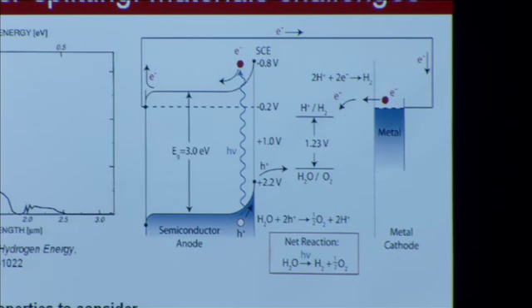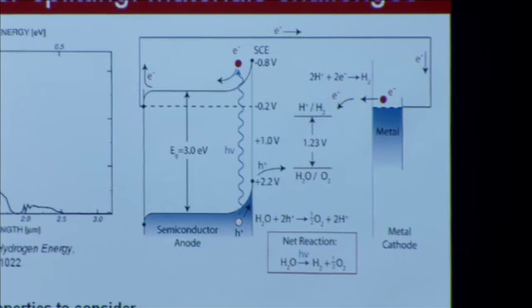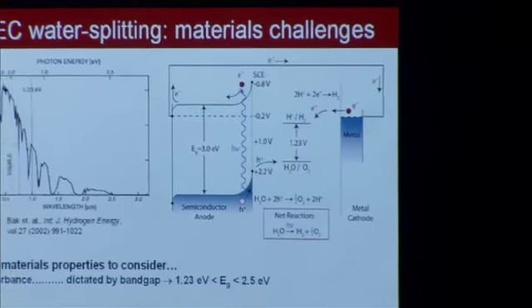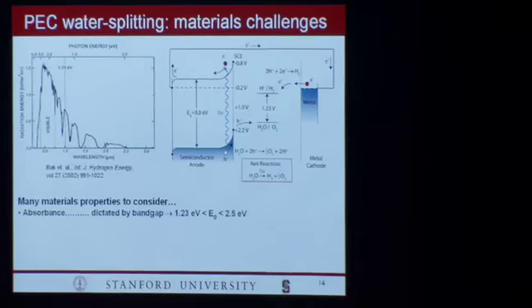So you say, okay, well, I want a bigger band gap so I have more photovoltage with which I can then split water. Well, that's true up to a certain point because as your band gap gets higher and higher, at some point you don't absorb enough sunlight to make for an efficient device to even hit 10%. So we're going to use these as hard limits. You really want your band gap to be somewhere between 1.23 eV and 2.5 eV, and that way you can get a lot of solar photon absorption and have the photovoltage needed to split water or reduce carbon dioxide. The magic number in this field typically is considered to be around 1.8 to 2 eV.